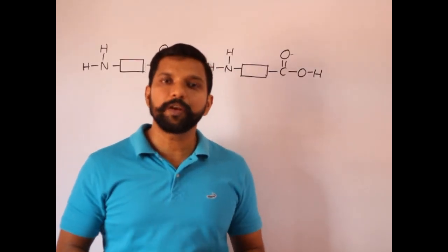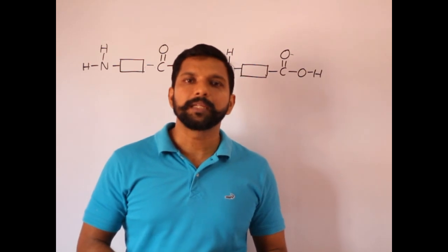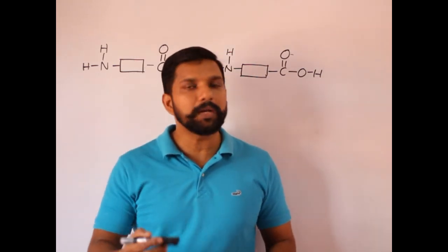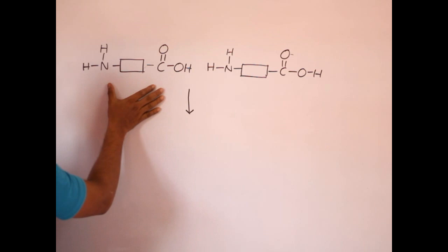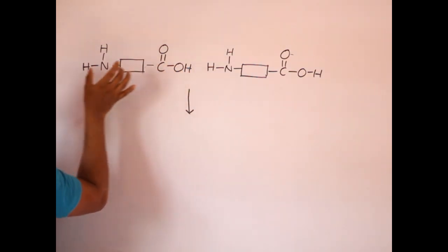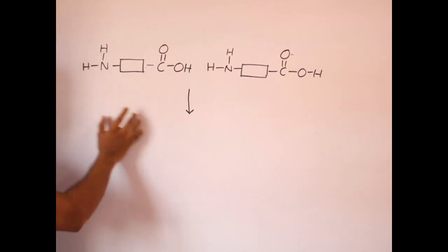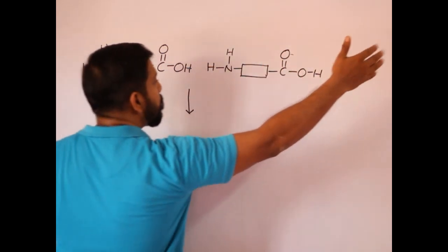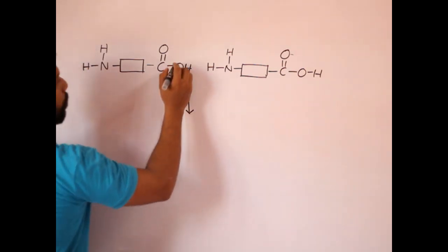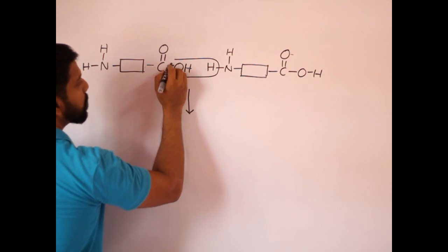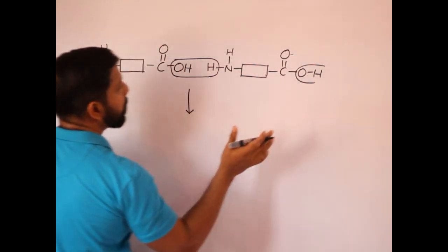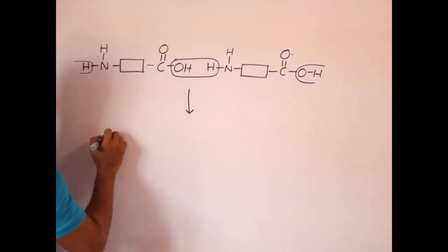Do we need 2 different monomers to form polyamide? The answer is no. Likewise in esters, we learn you can do it in one type of monomer. Here we have a molecule which has the COOH group and also NH2 group. And when we react this molecule with another molecule or with many of these molecules, you can have the polyamide produced. The OH group of the carboxylic group and the H from the NH2 will be removed, and that will continue from the other two sides also and giving you a macromolecule.